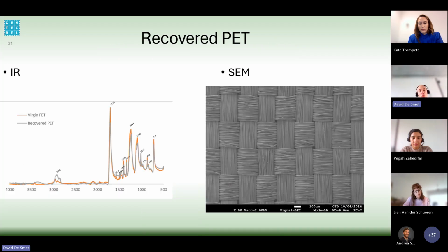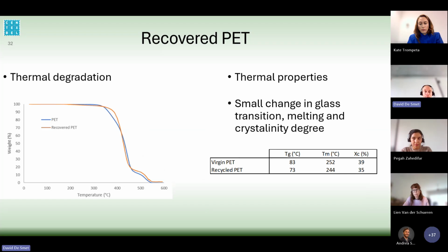If you look at the analysis of your fabric afterwards, which you can recover after the simple filtration process, you can see from infrared analysis that there's actually no really significant chemical difference or peak difference between the virgin and the recovered PET. So there's no chemical degradation of your polyester. Also, if we look at the SEM, so scanning electron microscopy, we don't see any degradation residue or impurities from the process on your polyester fabric.